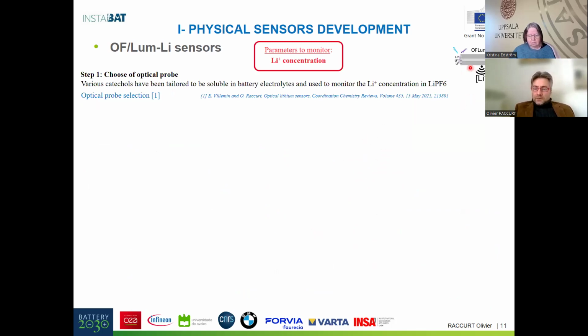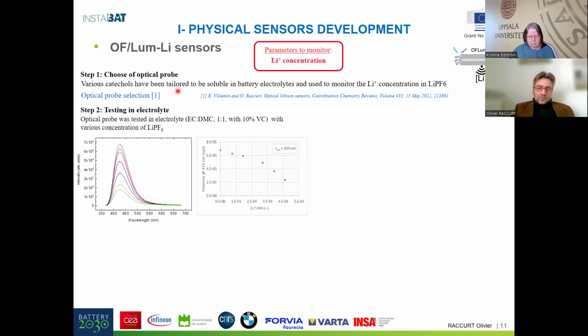Another kind of sensor based on luminescence I presented before is to monitor the lithium ion concentration. For that, we need to choose the optical probe. In the literature, there are a lot of molecules able to catch lithium in a liquid medium and to have a modification of the optical properties. And we analyzed this literature, and there is a good review on that to find the best molecules. But there is some difficulty because no molecules were previously developed to work in electrolyte, and it is a very particular medium because we are in carbonate solvent. And the work performed during the project is to adapt this molecule to work in this medium.